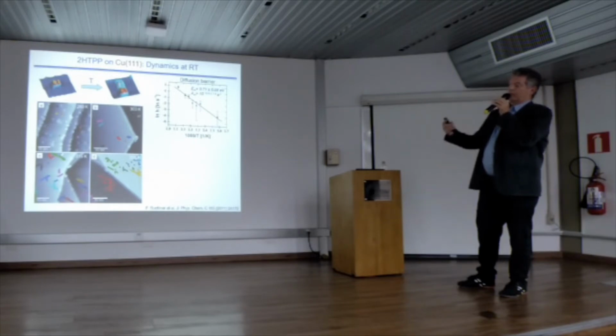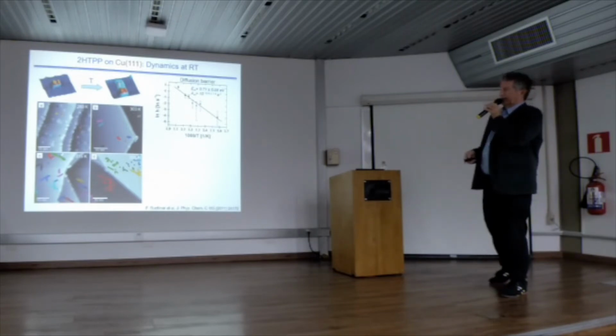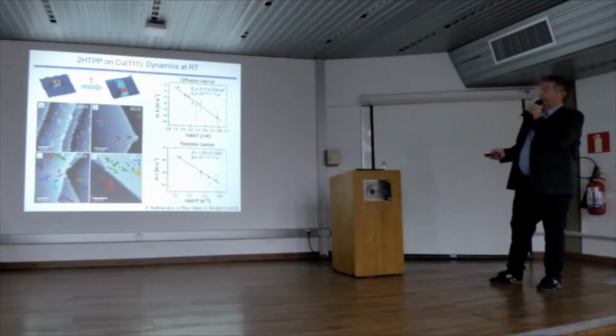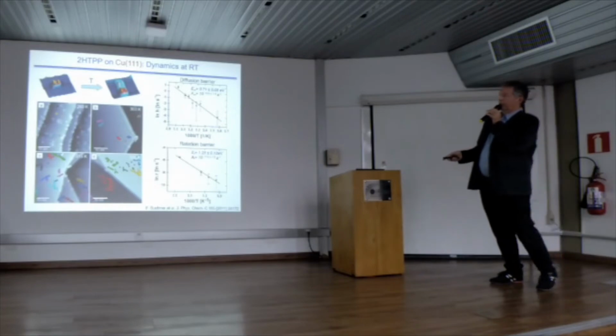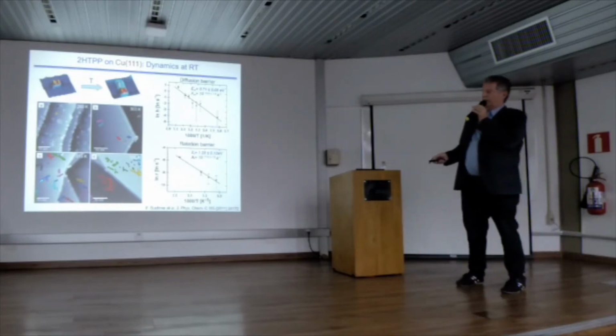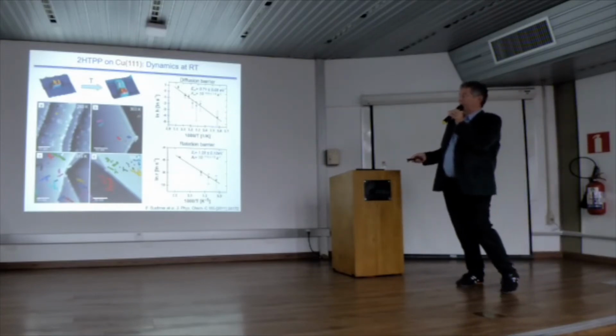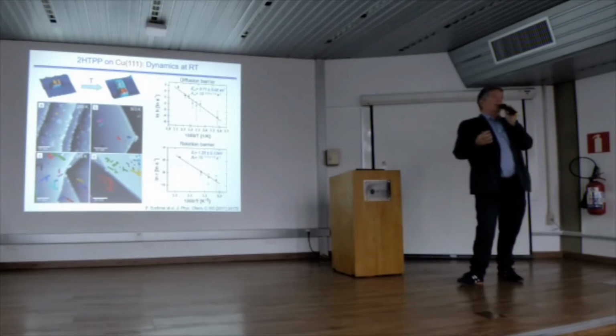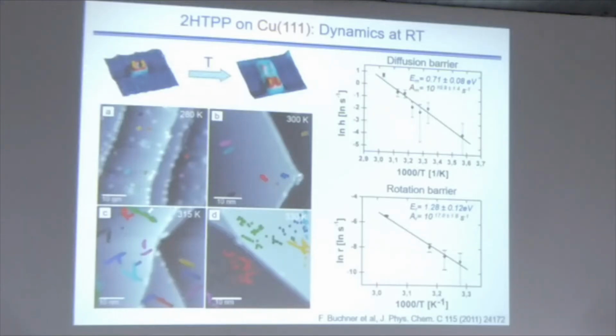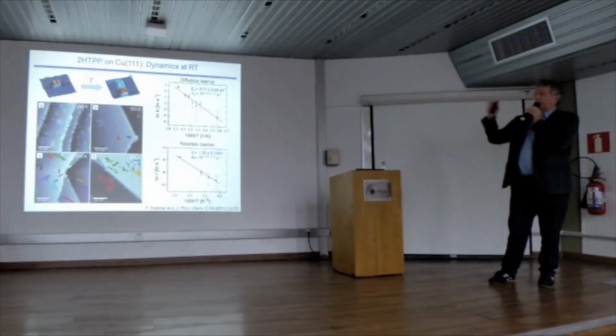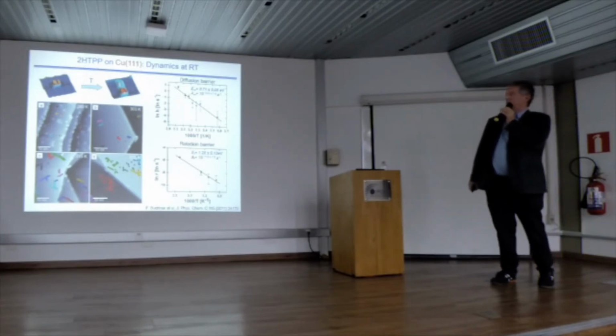So we call that rotation because the direction is rotated by 60 degrees. And again, we get a straight line, and we get a higher activation energy because in a very simple picture, this occurs more rarely, but on the other hand, the prefactor also changes. So that's a little more complicated, but I won't go into the details here. Okay, so this is work that is relatively old. This is 10 years old or so. And so we could quantify that, and that was really nice.